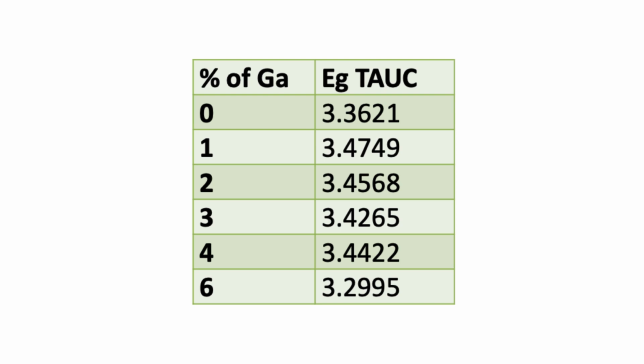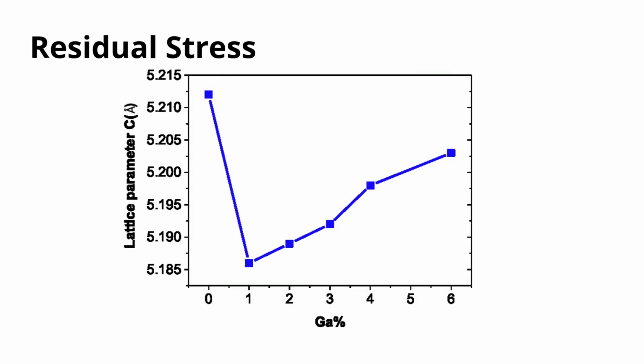The latter suggests that 1% to 2% gallium as dopant stimulated the displacement of the X-ray diffraction in the plane 002 diffraction lines, whose behavior increases the energy gap and minimizes the residual stress.